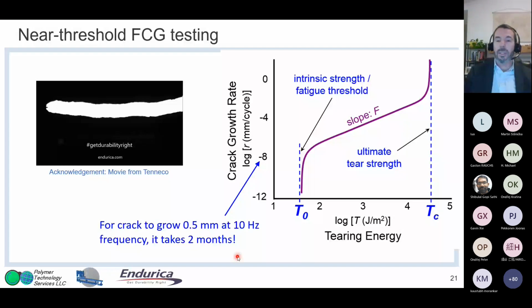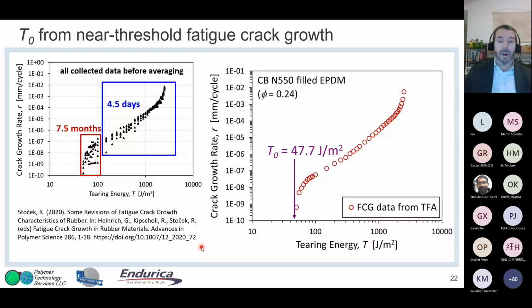And so you can start to see the problem with trying to use this method to define where this curve starts to turn downward. And obviously 10 to the minus 10th is even higher. One of the speakers today, Dr. Stocek, did a very nice job of doing this and really emphasized what we're talking about here. If you want to collect data in most of the crack growth curve, a few days is really all you need. And you can even have a really targeted crack growth testing that might take 1 day.